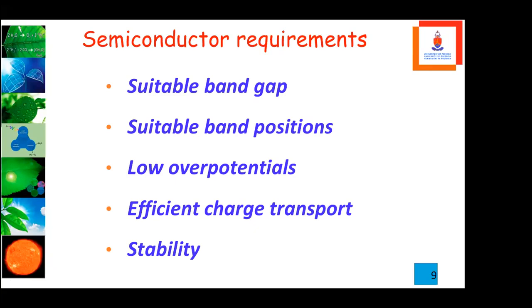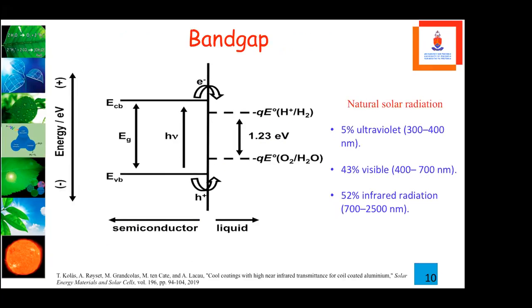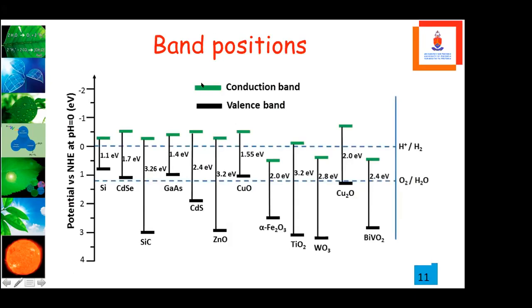Semiconductors used here have certain requirements. It must have a suitable band gap to absorb solar light, suitable band positions, which I'll explain quickly, low overpotentials, efficient charge transport, and stability in water. When we look at the band gap, natural solar radiation consists of 5% ultraviolet light, so it becomes difficult to use a material with a bigger band gap that absorbs in the ultraviolet, 43% in the visible, which takes most of it and is what we need, and 52% in infrared radiation. These are the band positions. That's your conduction band, and that's your valence band. This is your hydrogen production position, and that's your oxygen production position.